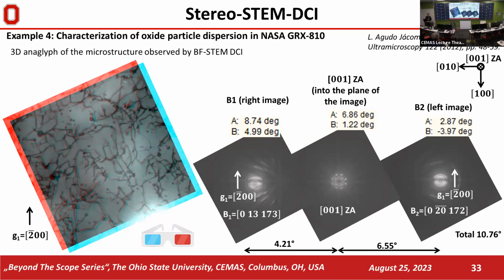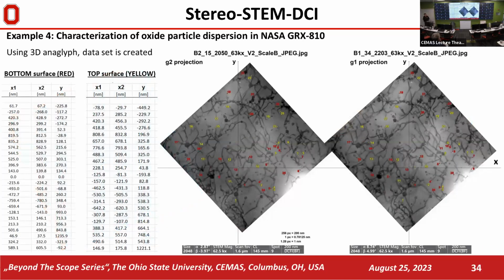Obviously we use the same g, that's important, and some orientation of the g for the contrast formation conditions. And then using these two images, we use freeware software, 3D Anaglyph Maker, and we form this image. Then we take red-cyan glasses, and we can see the structure nicely, but we can quantify that further. So we look at the anaglyph, and we put these two images of the structure with two different tilts into a coordinate system, and we extract information about intersections of different defects with the top and bottom surface of the foil, as we see it using red-cyan glasses on the 3D anaglyph. So we mark the positions of different defects scattered throughout the whole probed area, and we extract the set of data for the top surface and bottom surface.